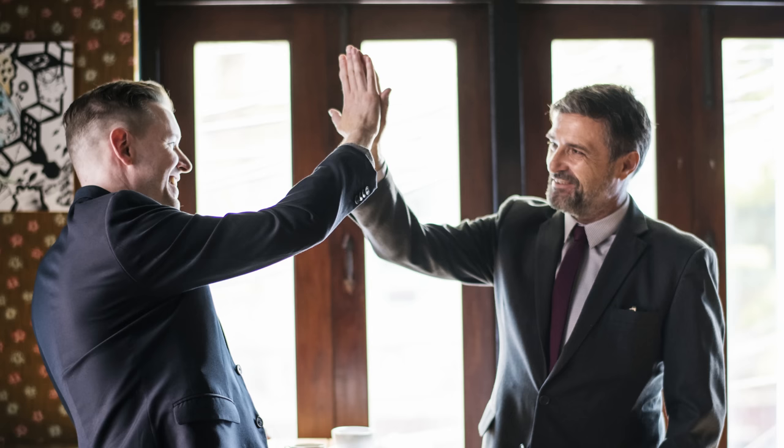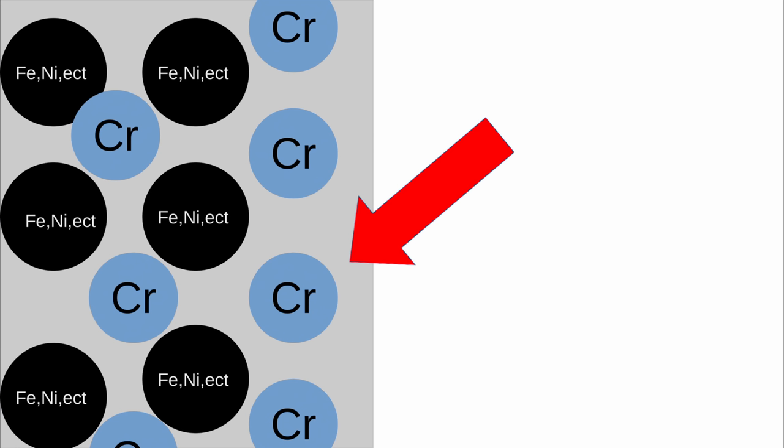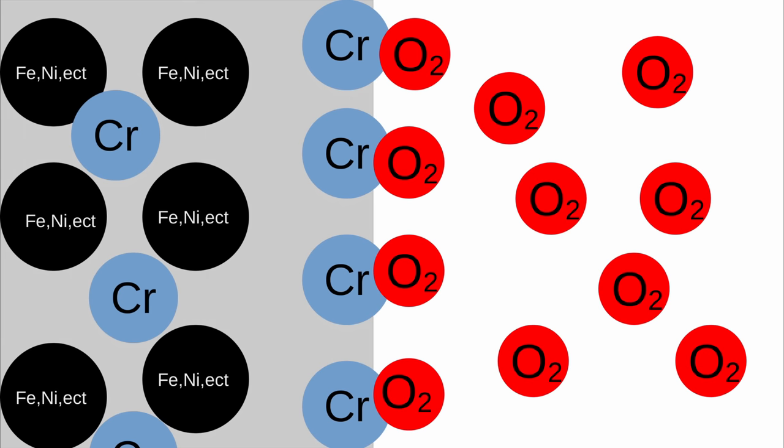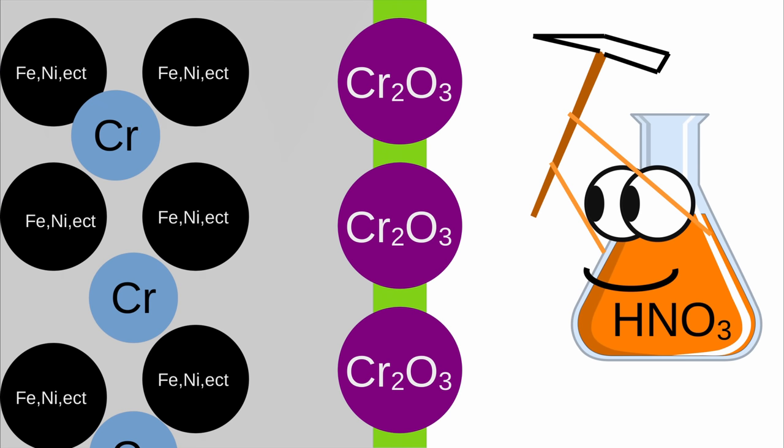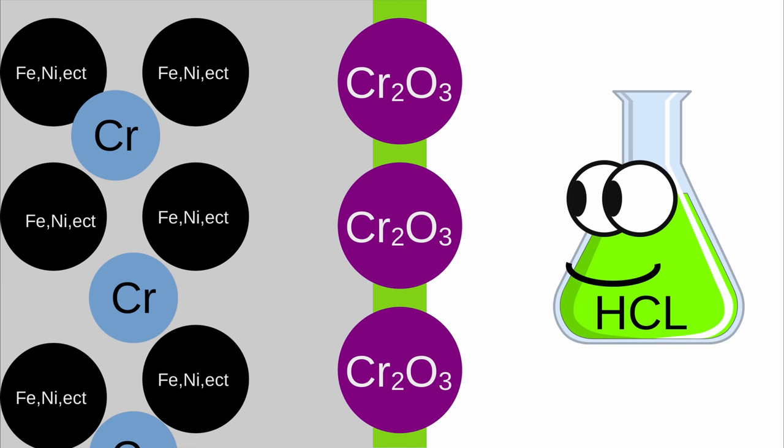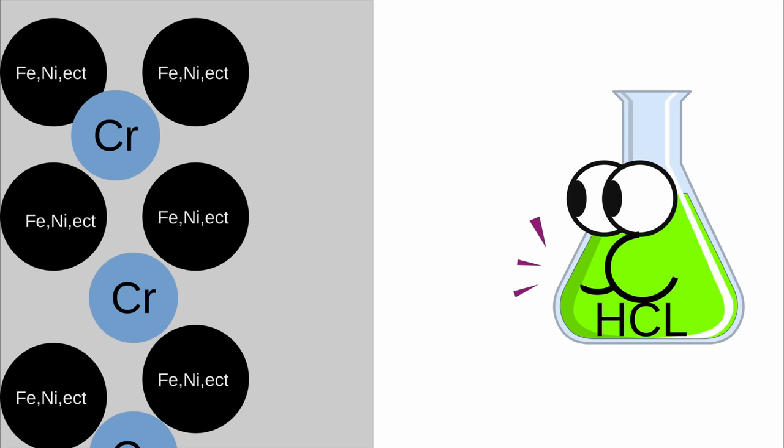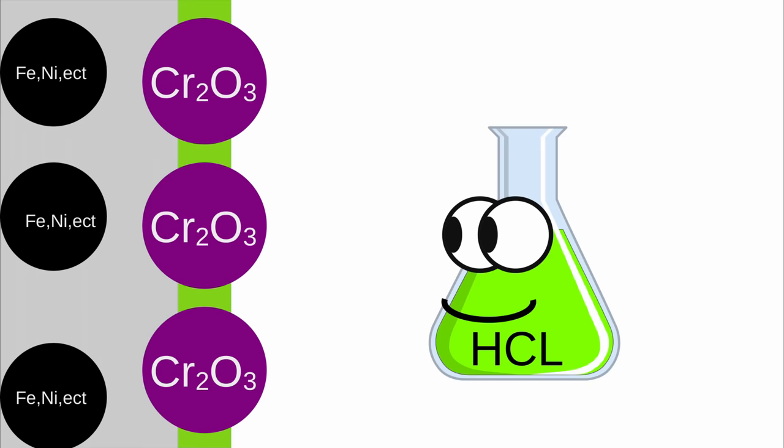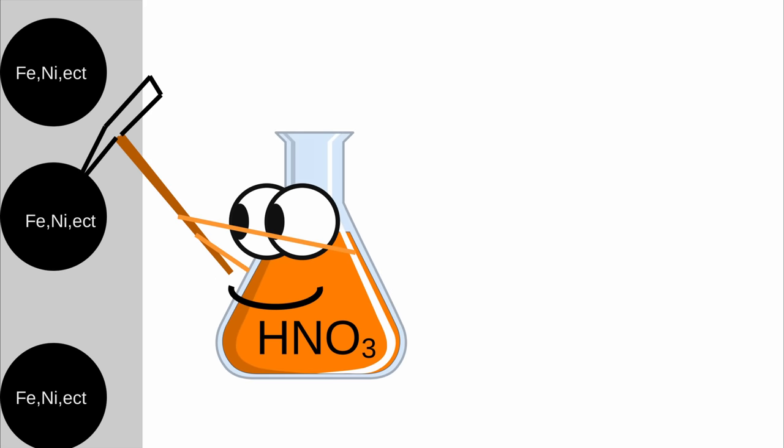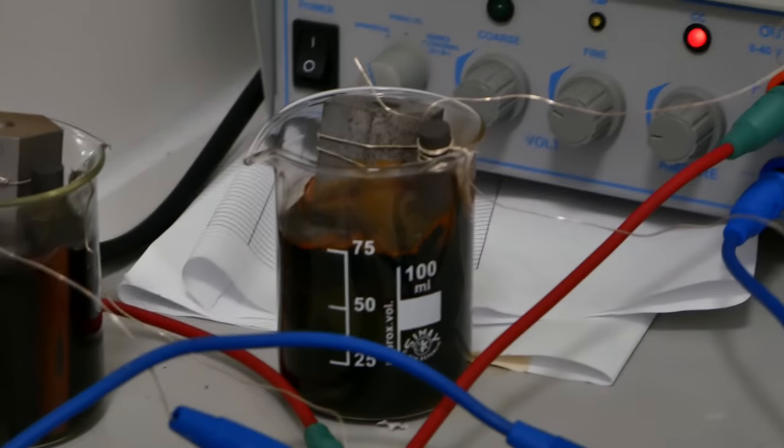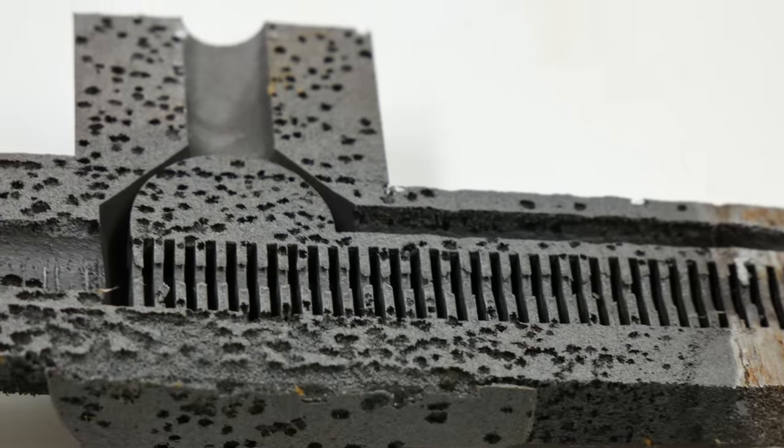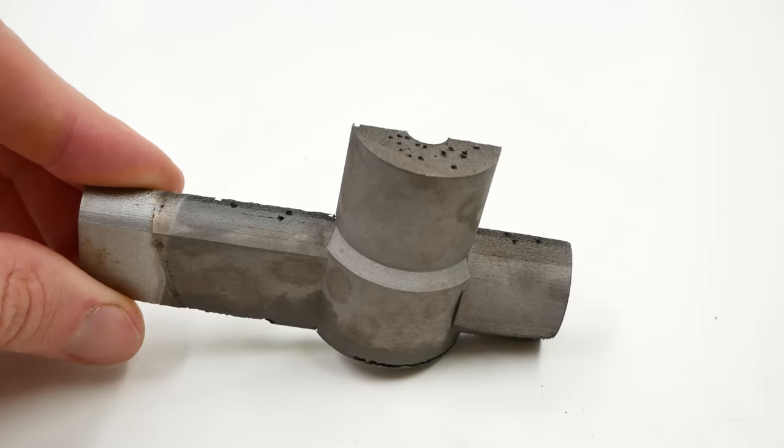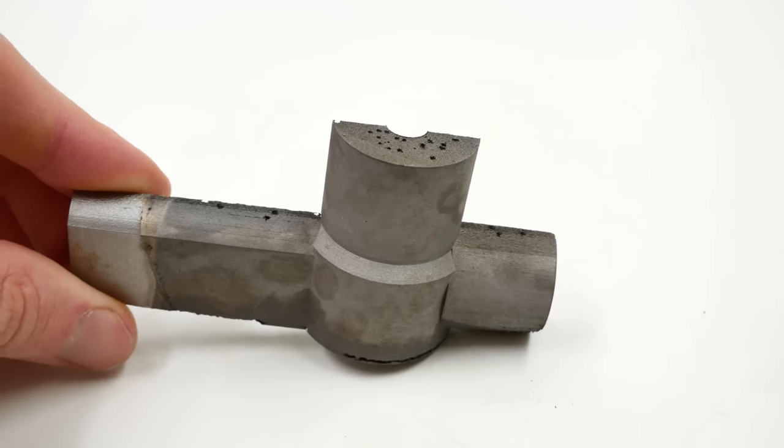The most important component of stainless steel is chromium, because if there's enough free chromium molecules in the surface of the stainless steel it will create an oxide layer that protects the underlying metal from agents that would usually dissolve it, for instance nitric acid. On the other hand, this oxide layer can be dissolved by hydrochloric acid, and with a mixture of the two you'll be able to dissolve stainless steel without any problems. Good job you two! Except we end up with a small problem. When you dissolve steel like this you do not get uniform dissolution, which means all the careful planning you put into the geometry of your valve is right out the window because it looks like a piece of Swiss cheese, and to make matters worse the support structures are still there anyway.